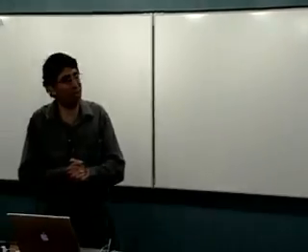And remember, the diffusion gradient I've been talking about is based on that. So Royce said what you really should do is use finite diffusion, not semi-infinite. The argument was that people were getting away with it because they had rather thick layers on the surface, and they were only oxidizing or reducing part of the layer, and so the condition held. But if you were going to oxidize the whole thing, there was not a chance it was going to work.